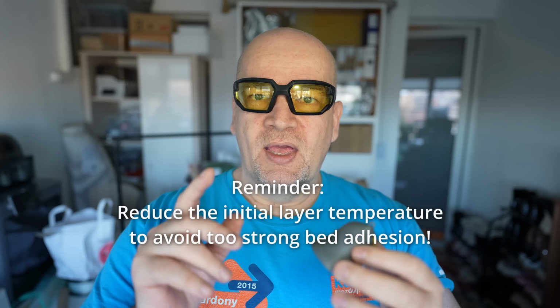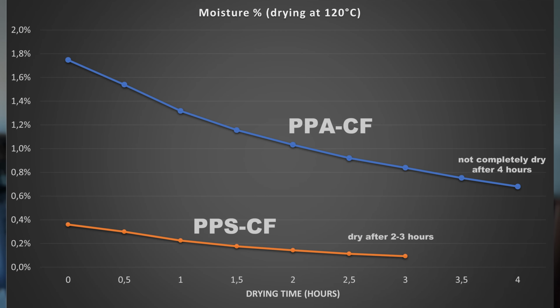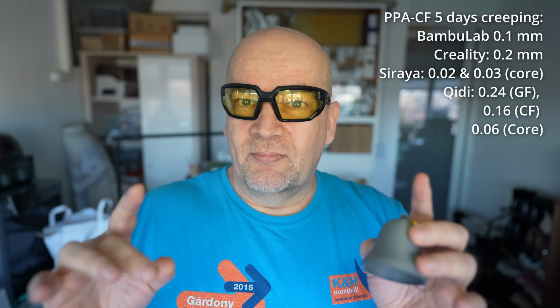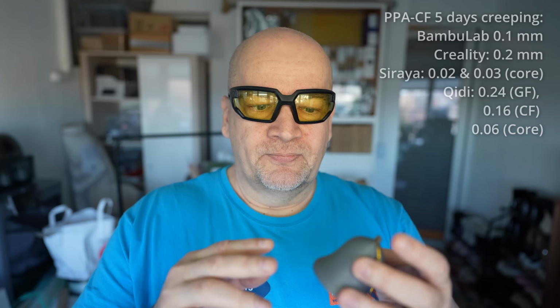And very often I get the question, PPS or PPA? Well, PPS has higher temperature and chemical resistance, it is less sensitive to moisture, and it looks like it is less sensitive to creeping. Basically, I could measure zero creeping with the PPS filaments, and with PPA it was very minimal, but it was there, it is still a nylon. This was my experience with the PPS filaments.